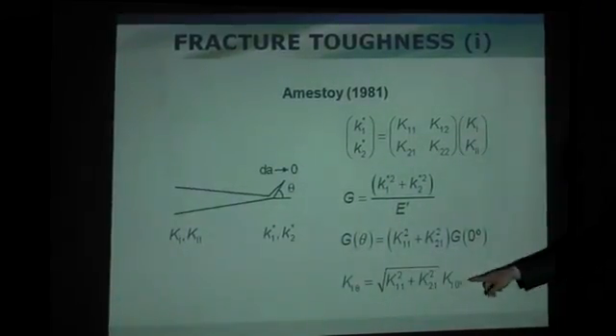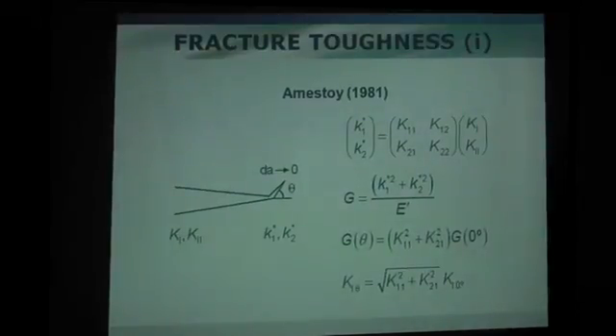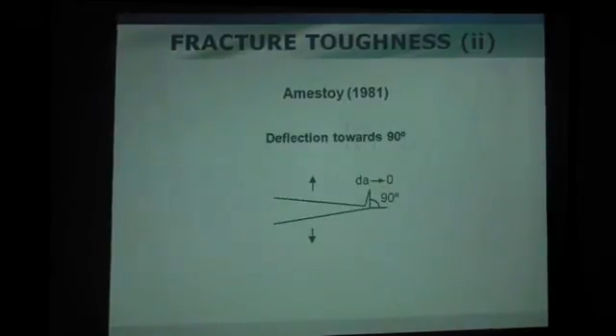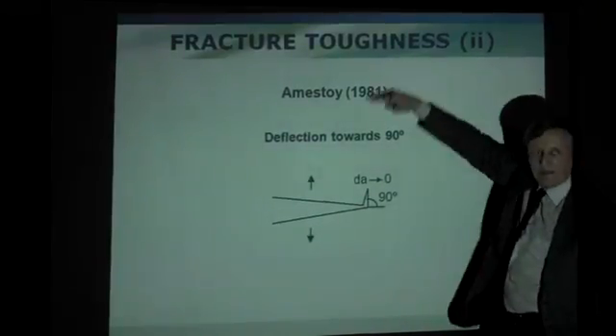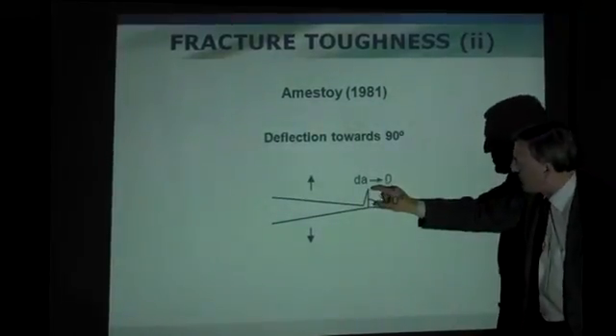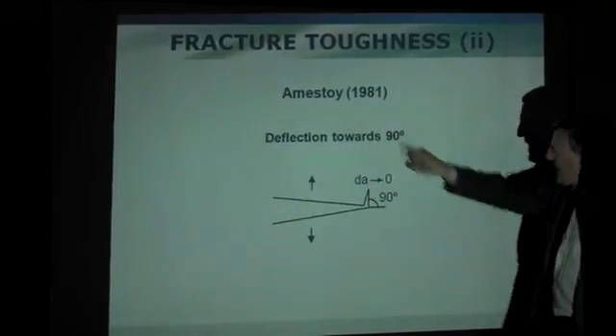K1 theta as a function of the K1 in zero direction, in transverse direction. Yeah, this is the hypothesis of our group. This is not by Amestoy, sorry. We use the mathematical equation by Amestoy, but we produce this deflection towards 90 degrees.